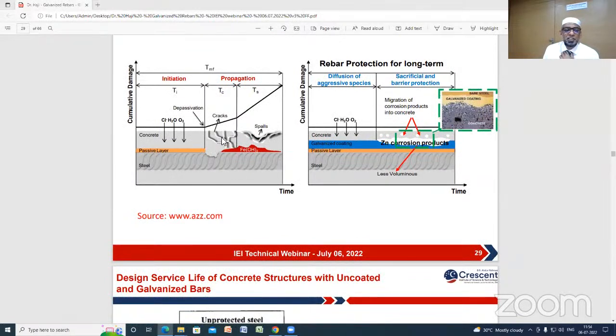This picture clearly shows that in the galvanized rebars, you can see that a passive layer is forming. After that, this passive layer destruction itself will take a longer time. After that, zinc only corrodes and steel will not corrode. Once all the zinc is consumed, then only steel starts corroding. So it will take a very long time for the corrosion initiation in steel. Based on the expected environmental conditions, we can design the thickness of the coating. Accordingly, we can achieve the desired, trouble-free service life.